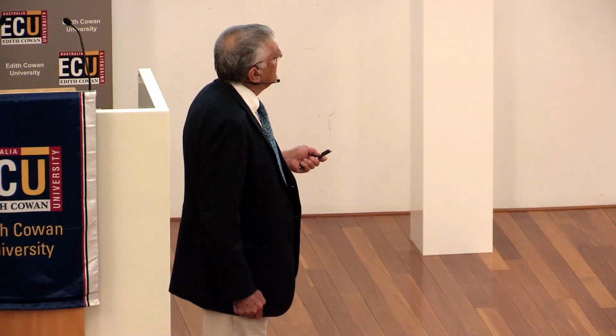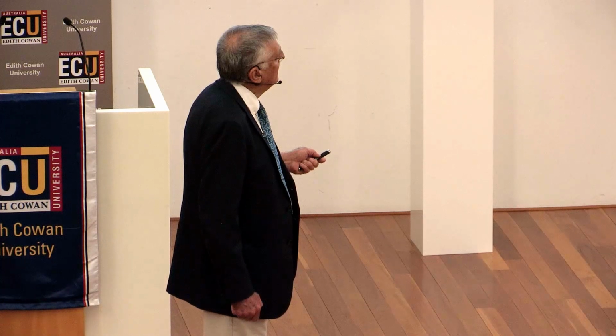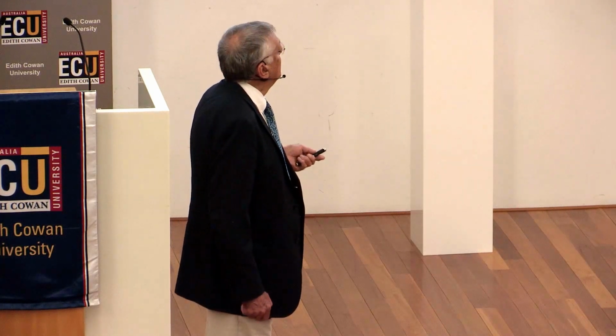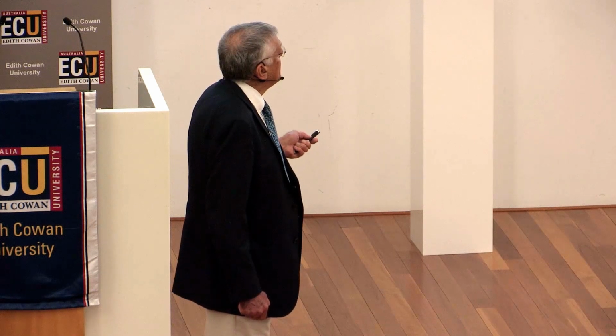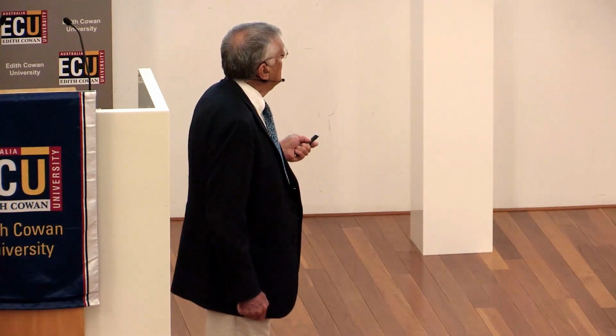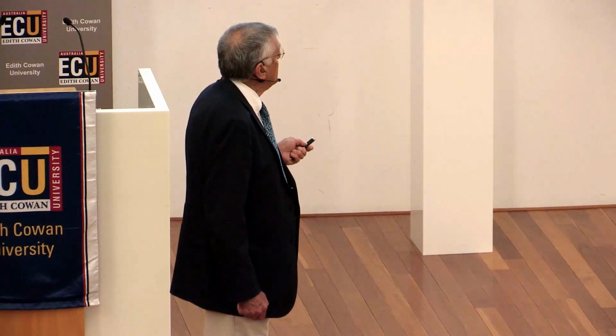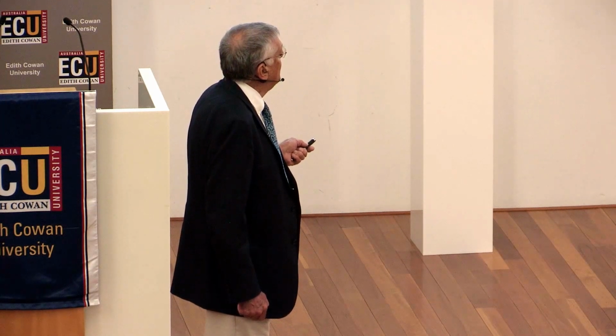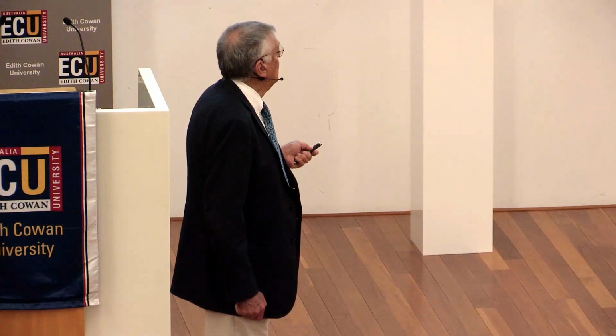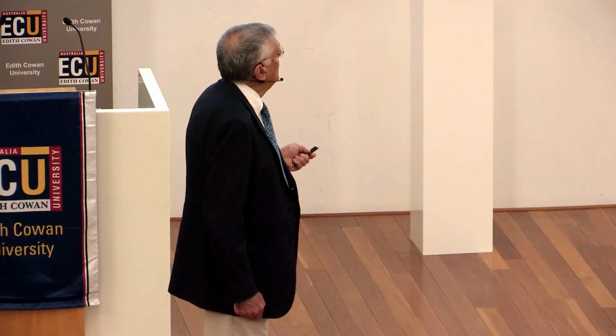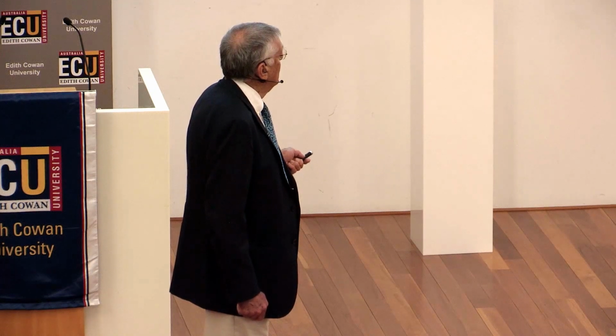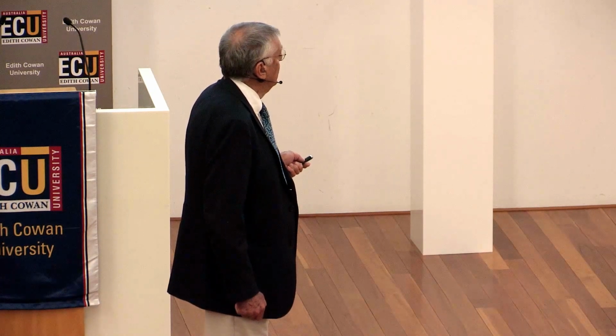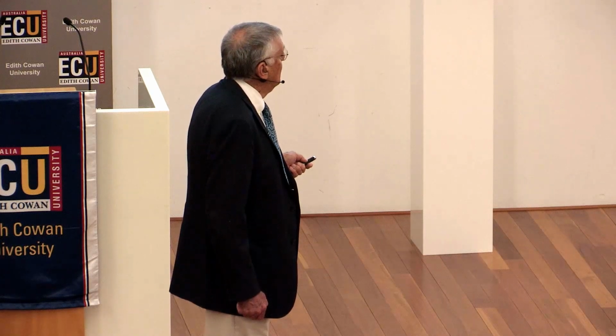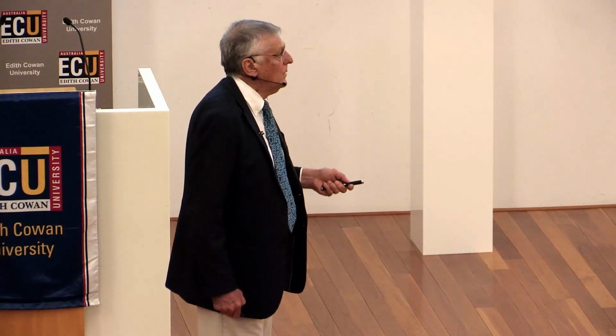But I was looking for periodicity. No periodicity. All right? Look at the distances. You take these distances, multiply by 2, you get here. And there is nothing there. So, no periodicity. The ratio of distances between the central spot and other spots is the Fibonacci number tau. I raise the memory of Mr. Fibonacci of Pisa, and that number is called tau or phi, known also as the golden mean. This is the number 1 plus root 5 divided by 2, 1.618, an endless number of digits.